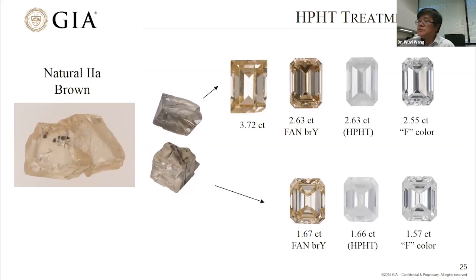This is the diamond treatment we did in GIA. A very large type IIa brown diamond we purchased, laser cut in two halves, and then went through the polishing. When fully polished, it's a beautiful brown color. After HPHT treatment, as you can see, the brown color is entirely removed. The surface is a little bit frosted, as you can imagine, because the diamond stayed at a very high temperature. And then after repolishing, which loses very little of the stone, it turns out to be a beautiful colorless diamond.